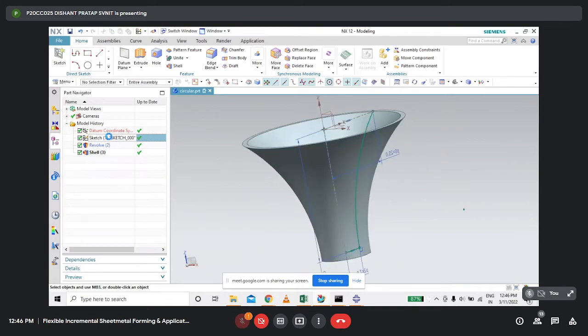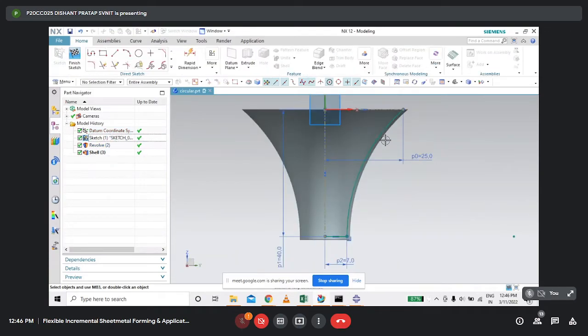First, I have created this geometry, a variable wall angle conical frustum, and at the bottom of this I have a geometrical constraint that the angle is 90 degrees. As I have already told you, the final thickness of the part depends on the forming angle: TF equals Ti cos alpha. Alpha is the forming angle, so we are changing the angle, and if the angle reaches 90, fracture usually happens because thickness reduces to 0.